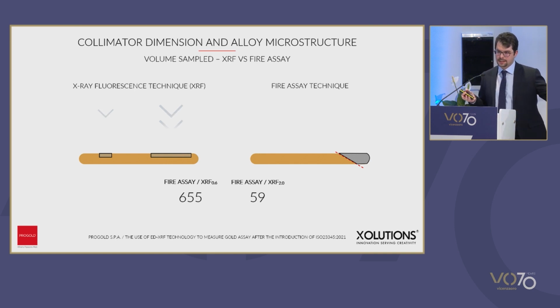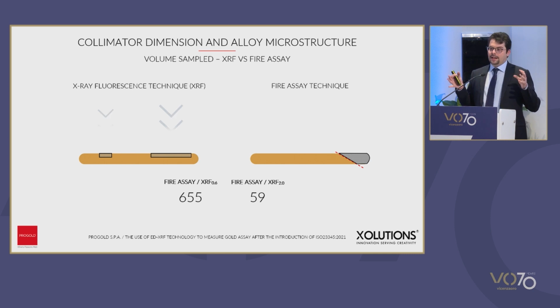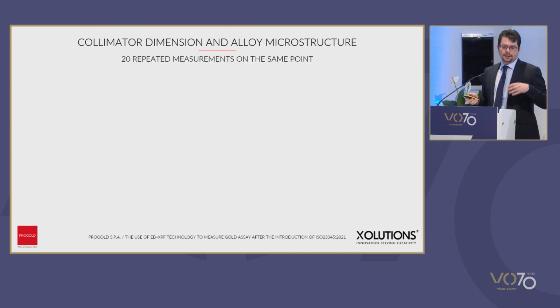And if we use a smaller collimator, which is on the left, the fire assay will involve 655 times more atoms than the XRF analysis. But if we increase the size of the collimator, this ratio will go down dramatically, down to 59 times. And this suggests that the bigger the collimator, the more the quantity of atoms is similar to the technique used for fire assay.